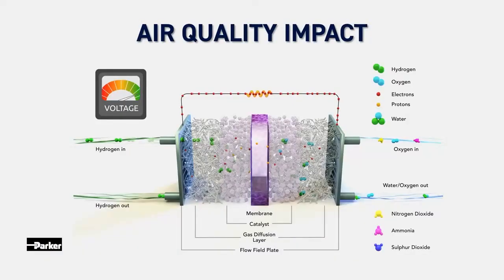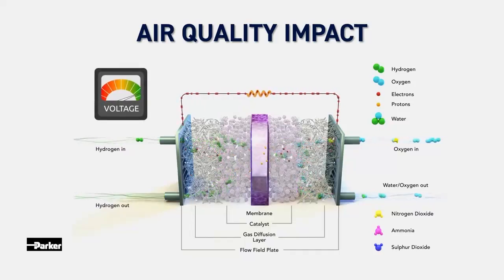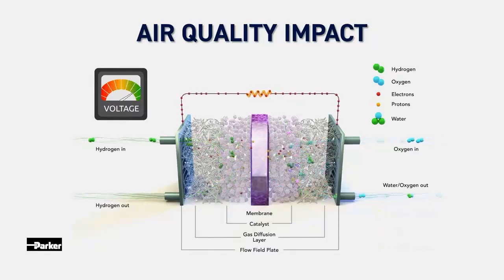The fuel cell stack is very sensitive to impurities. The quality of the hydrogen and of the air needs to be controlled before it reaches the stack. Certain gases, such as nitrogen oxide, sulfur dioxide, ammonia, toluene, and others, which are present in the air, can poison the catalytic layer. This will block the platinum catalyst and can lead to power losses because the electrochemically active surface is reduced. The poisoning effect of some of the gases can be reversible, but for others it cannot. For this purpose, it is critical that these contaminants are filtered out before the air reaches the stack.